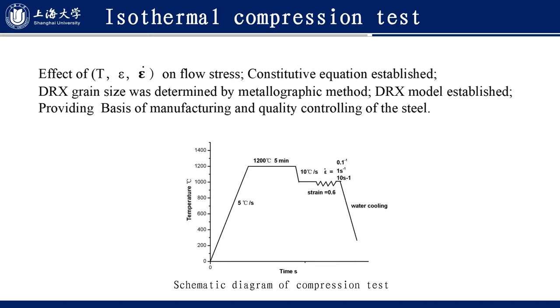In this test, the effect of temperature, strain, and strain rate on flow stress, the constitutive equation, and dynamic recrystallization grain size was determined by the metallographic method, and a dynamic recrystallization model is established. It can provide a basis for manufacturing and quality control of the steel.